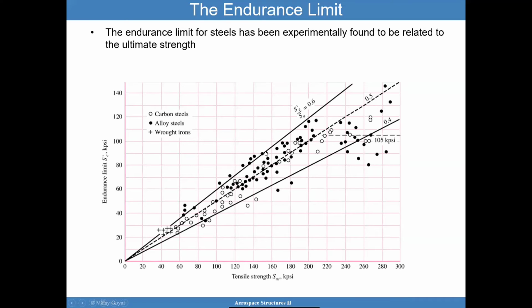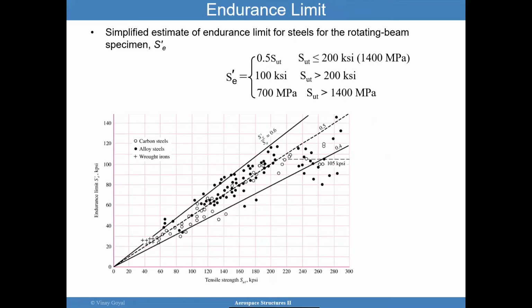If you look at the upper limit, you're looking at 0.6, the lower limit closer to 0.4, but you have a lot of extra data out here. And then on average, 0.5. That is the ratio of SE divided by SU, the tensile strength. Here's some information that could be useful from a rotating beam specimen. SE prime is 0.5 SUT, and then 100 KSI for tensile strength greater than 200 KSI. So basically, at this point you draw a line and say, okay, just use 100 to be conservative.